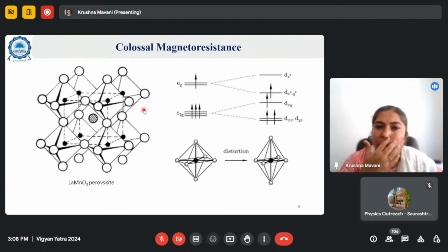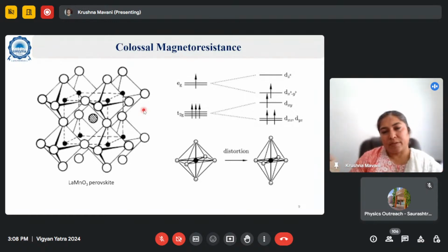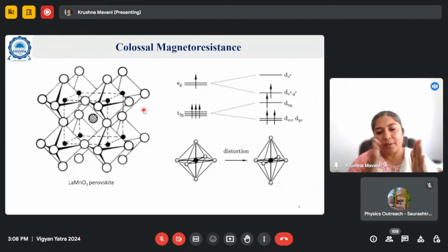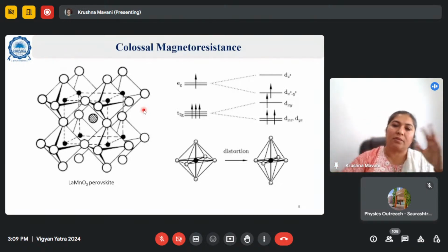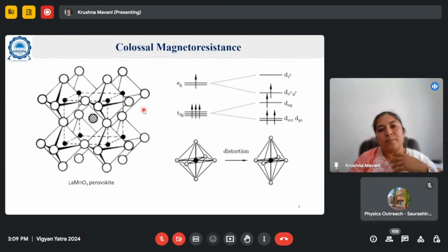So there is another phenomenon, colossal magnetoresistance. The values of this magnetoresistance are quite comparable to giant magnetoresistance, but the principle is slightly different. In giant magnetoresistance, you had multiple layers, right? Here you have just chains of manganese, oxygen, manganese ions. This manganese, oxygen arrangement across the crystal structure will be actually participating in the charge conduction.